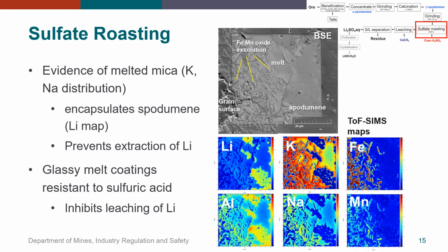The upper backscattered image shows the main textural features of the region of interest examined by TOF-SIMS. It is thought the manganese and iron oxides in the backscattered image, and as shown by the element mapping, formed by the exsolution of iron and manganese incorporated in spodumene, and possibly mica, during calcination. TOF-SIMS element mapping shows evidence for the presence of glassy melts from the potassium and sodium distribution maps, which surround regions with relatively high lithium contents of unleached spodumene. These glassy coatings are resistant to sulfuric acid and inhibit the leaching or removal of lithium.